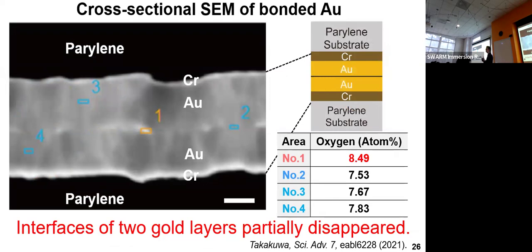And here, number 1 point, you can see the colored interface regions. So these regions imply there was an interface. But anyway, we could make almost perfect bonding with these simple processes. And then here, this number 1 region shows a little bit higher oxygen amount. So we guess, firstly, such OH bonding makes weaker bondings at the interfaces. Then later, such OH bondings can be replaced with metal bondings, the gold-gold bondings, to make stronger bonding